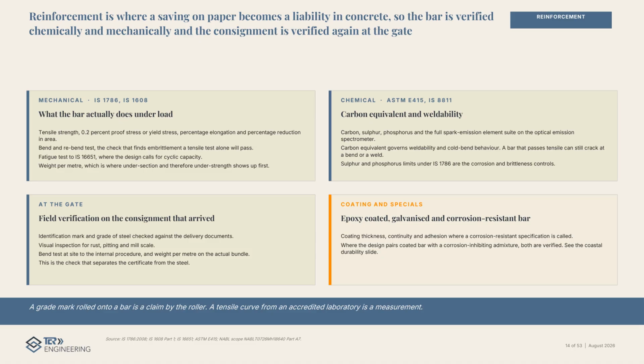Mechanically, we run tensile strength, 0.2% proof stress, elongation, reduction in area, and the bend and rebend test, which is the check that finds embrittlement a tensile test alone will pass. Chemically, we run carbon, sulfur, phosphorus, and the full element suite on the spark emission spectrometer, because carbon equivalent governs weldability and cold bend behavior. And at the gate, we verify the identification mark, the visual condition, and the weight per meter of the bundle that actually arrived. That last one is what separates the certificate from the steel.